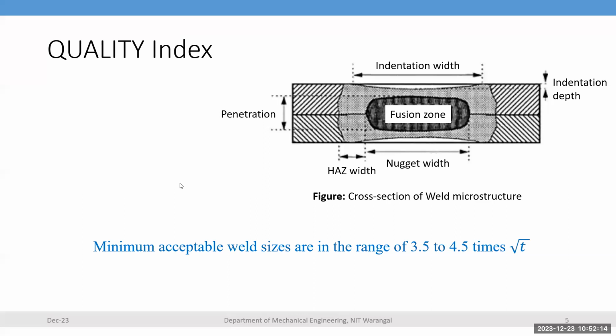Then how to judge the quality of the resistance spot welding. You can see the cross section of the weld microstructure in between the two plates, because the material is melted. Partially the material is melted, not fully. So only a partial region is melted in between the two sheets, and you can apply the pressure so that the weld is solidified during the period of time.